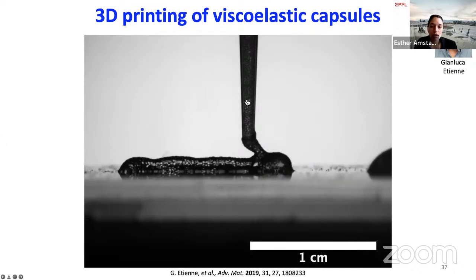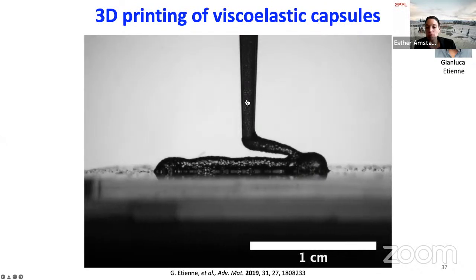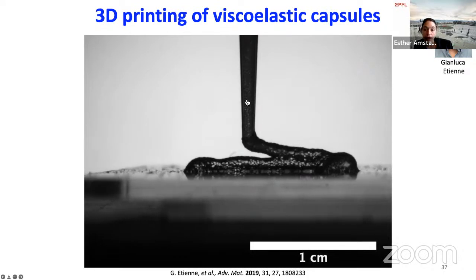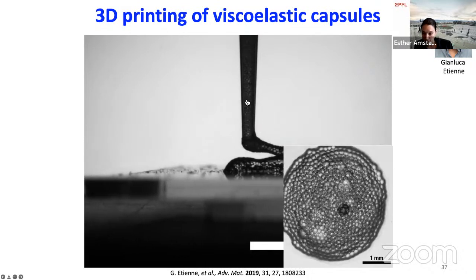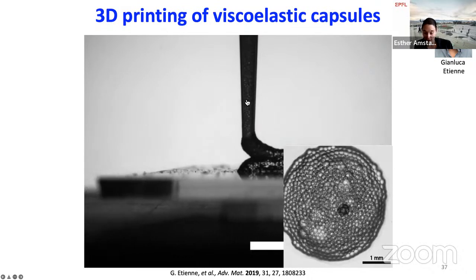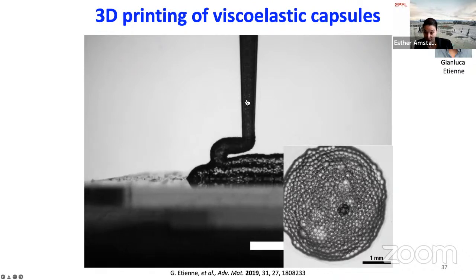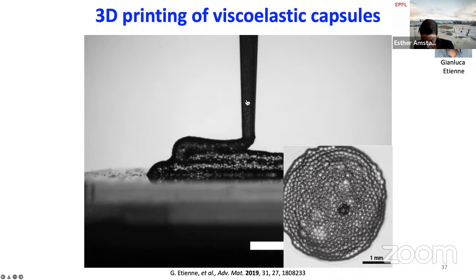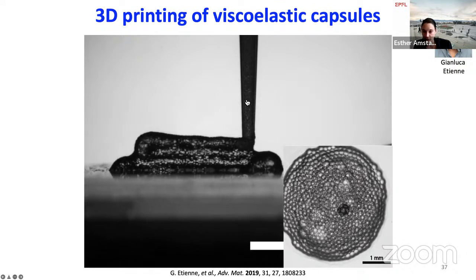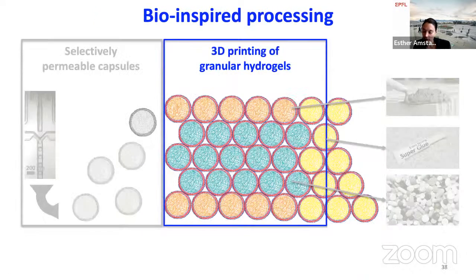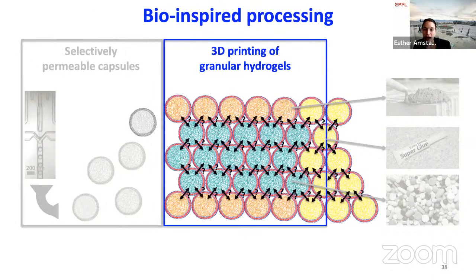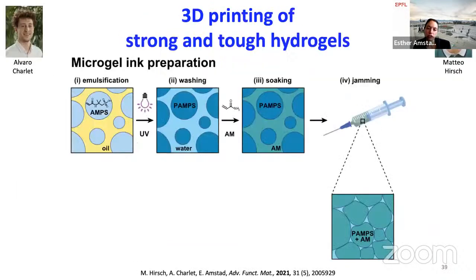This was very preliminary results, but we showed that we can extrude them and that the granular structure is retained, even if we have these viscoelastic shells that are still filled with liquid. So it's not a real solid material. It's more like a foam-like structure. How can we convert that into something load-bearing that I really would like to get at the end? So how can we connect these particles more strongly to each other?